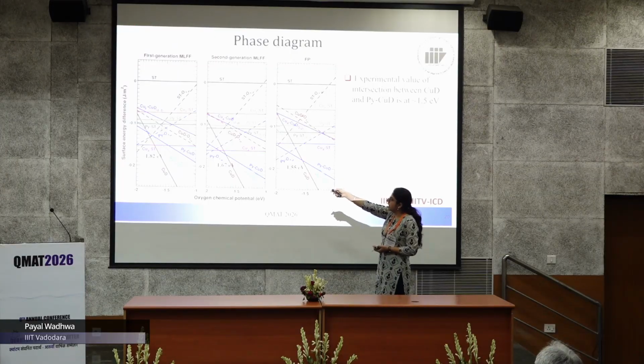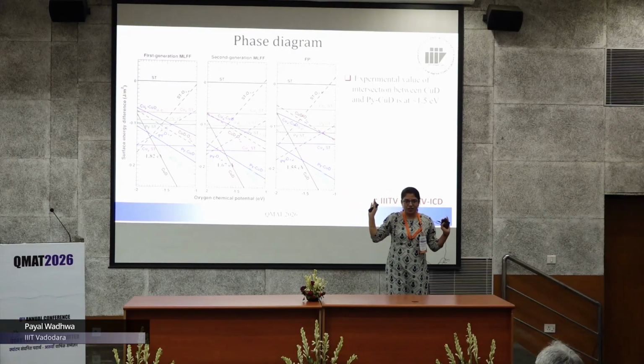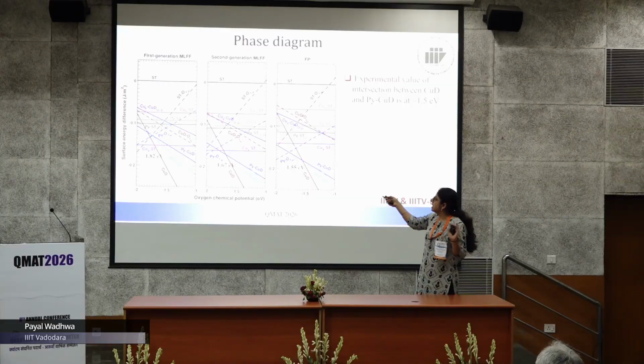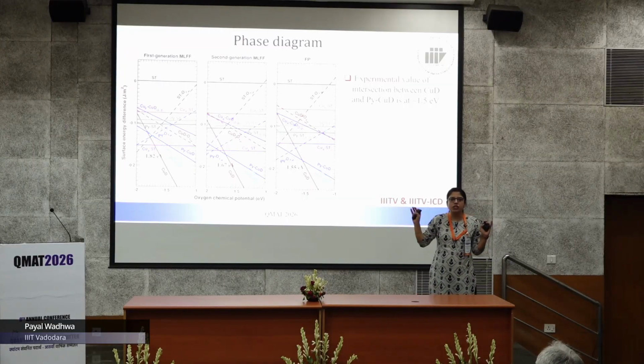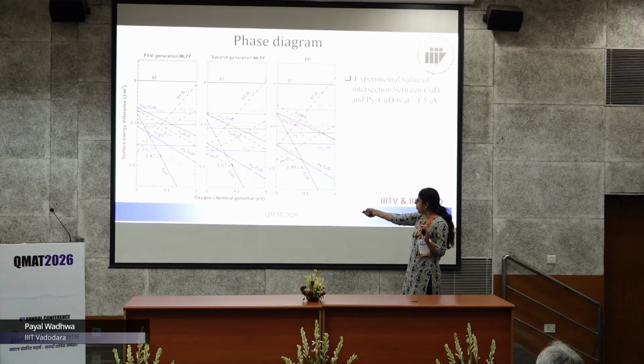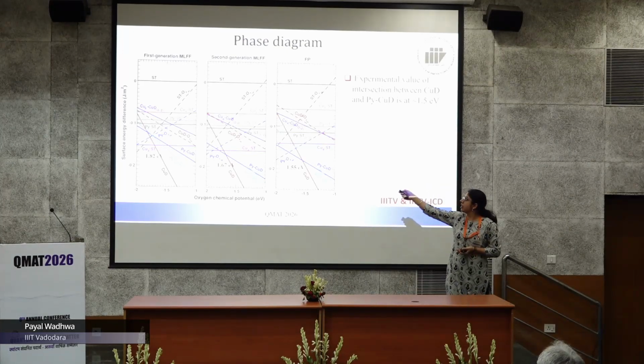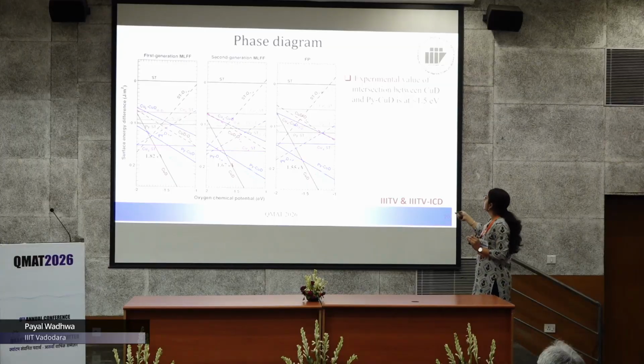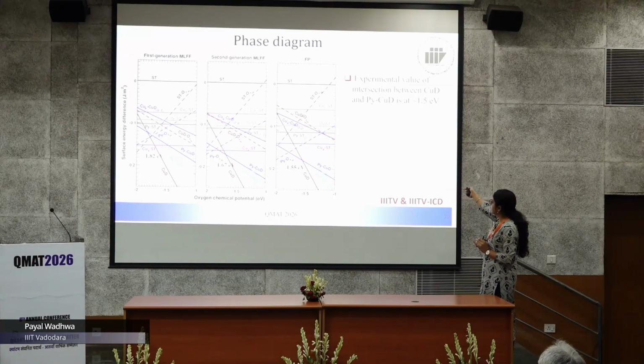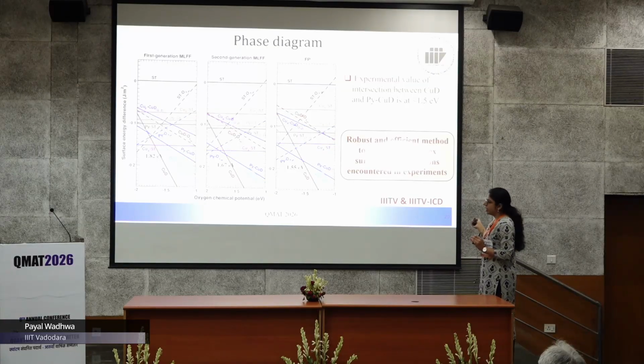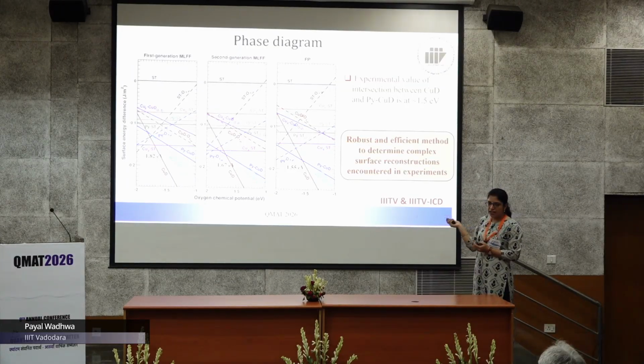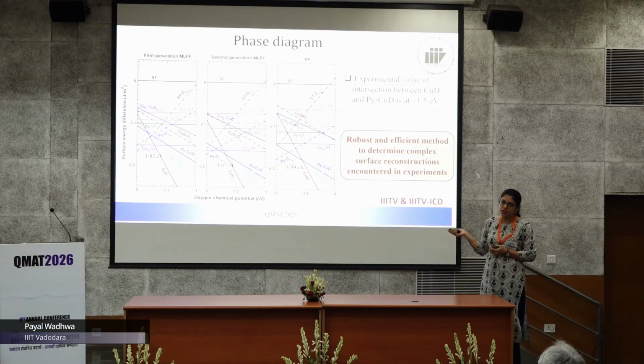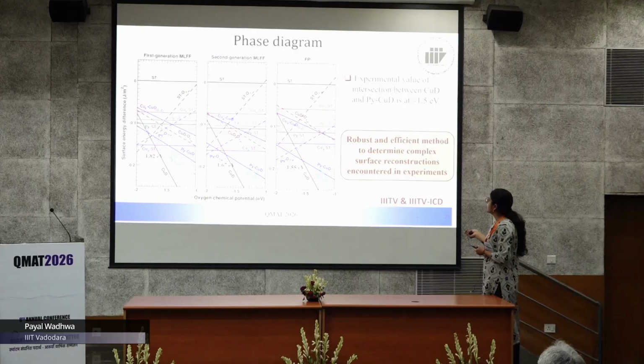Of course, the first generation is good in determining their structures, but if you want to determine the energy, then the second generation would be better because it has more structures of copper deficient as well as copper rich. So their intersection point indicates that our model is robust. It is also in good agreement with the value provided by our experimental collaborators at like 1.5 eV. So it indicates that on the fly training provides a robust and efficient method to determine complex surface reconstructions commonly encountered in experiments.